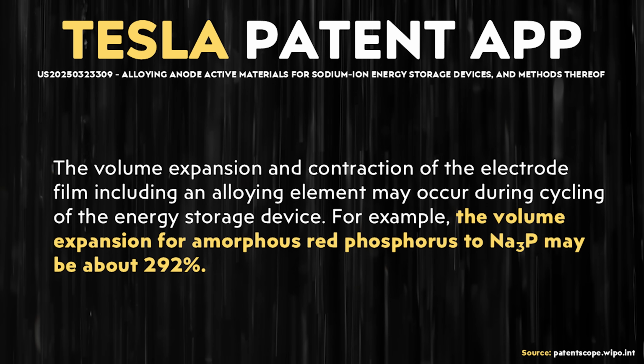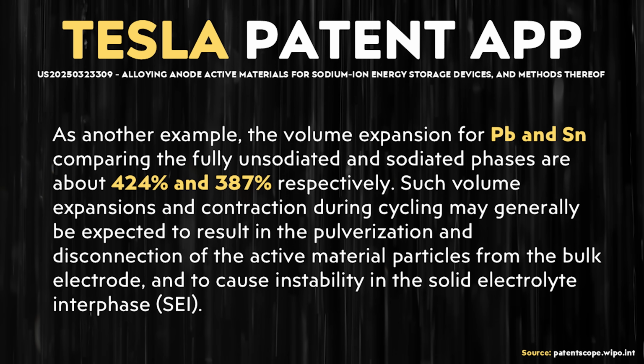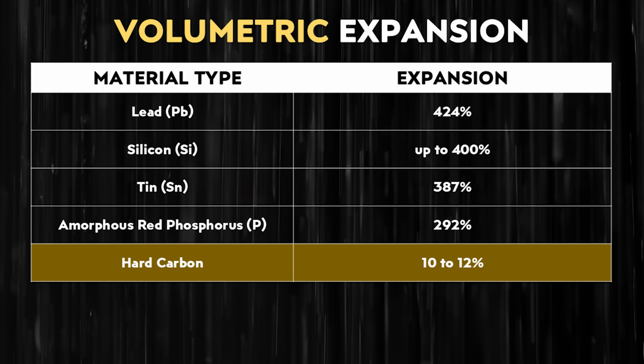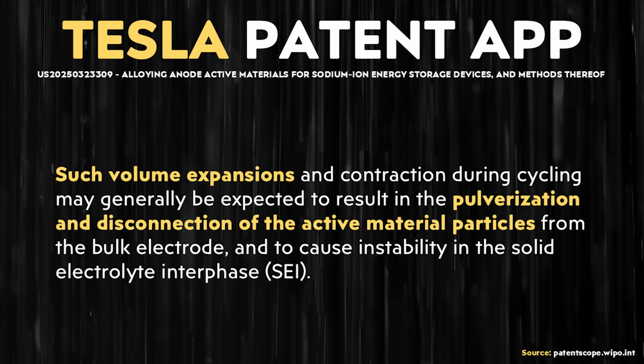As is pointed out in this text, quote, "the volume expansion for amorphous red phosphorus to sodium 3P may be about 292%. The volume expansion for lead and tin, comparing the fully unsodiated and sodiated phases, are about 424% and 387% respectively." When it comes to how that volumetric expansion compares to silicon and carbon, tin and lead, for example, are in the range of what silicon can see when it comes to volume expansion, with lead being even higher than silicon, for example. So as is pointed out in this text, you would think that with that kind of volume expansion, this would cause problems in a battery.